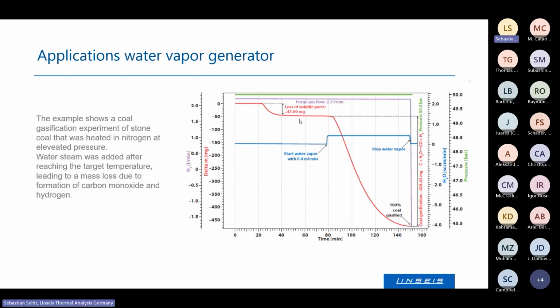Once you reach the target temperature, we switched from just purge gas to water steam, activating the steam generator around 80 minutes, somewhere here. Once water steam reached the sample, the so-called gasification reaction started - the bound carbon reacted with water to form carbon monoxide and hydrogen. This reaction even goes on to form methane in the very end.